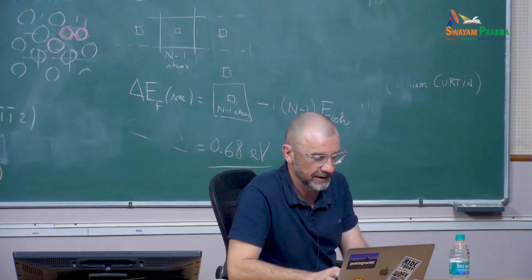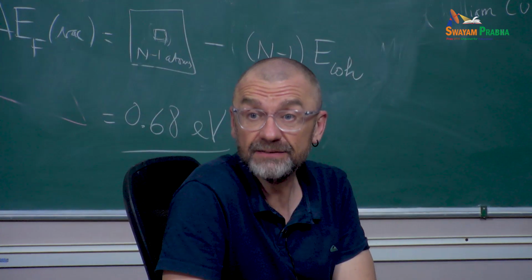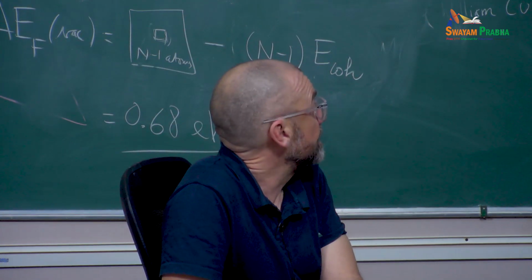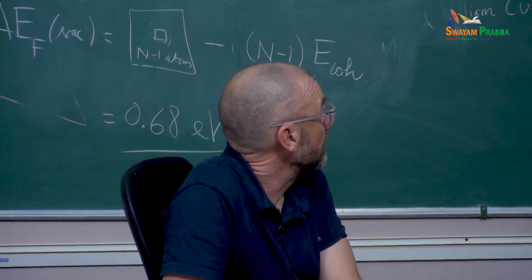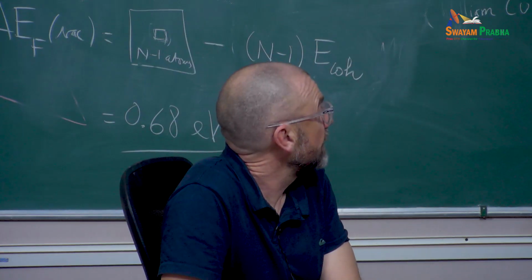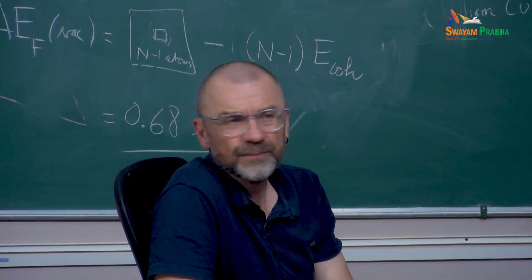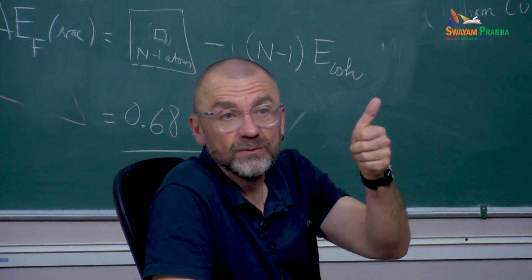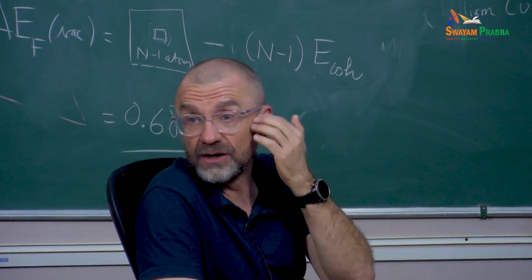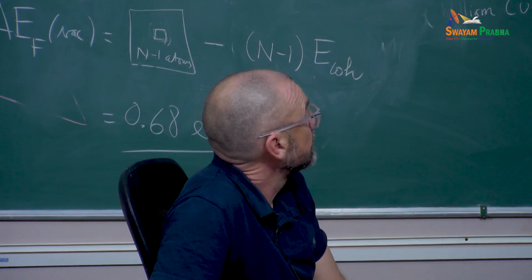So to get there, maybe we can have a look at the script to compute the vacancy formation energy. So the beginning is the same as always: metal, atomic, map hash, periodic boundary conditions everywhere. Now, what changes compared to before? This is where I create the crystal. What did I change compared to before? So I'm starting with the correct lattice parameter. Now I know it's 4.032, so I'm using it here. And the other difference is what?